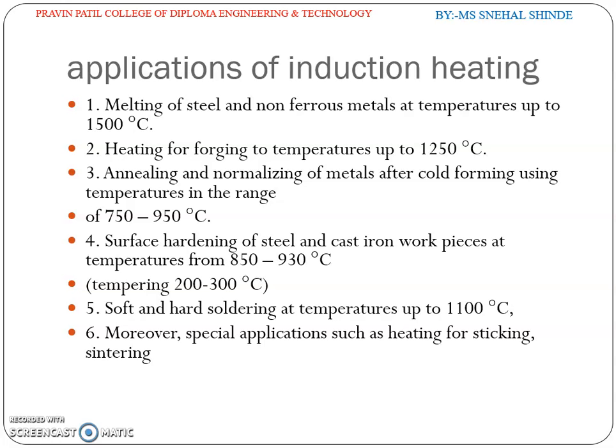Now what are the applications of the induction heating? Induction heating is employed for various industrial applications such as soldering, brazing, heat treating, including hardening, annealing, melting, sintering powder metals, drying paints, sterilizing surgical instruments, bonding, clutch facing. So the applications are melting of steel and non-ferrous metals at temperature up to 1500 degrees Celsius, heating for forging to temperature up to 1250 degrees Celsius,